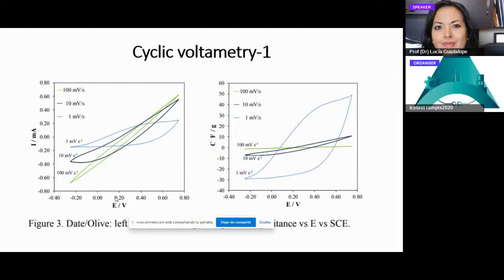to check what will be the facility for some ions going to the surface and how the time affects this. When you apply a slow scan rate, you can give the time to the ions to move to the surface very well. And as you can see in this second one, the specific capacitance diagram, at 1 millivolt per second we can have bigger values in Farads per gram in capacity of this material.